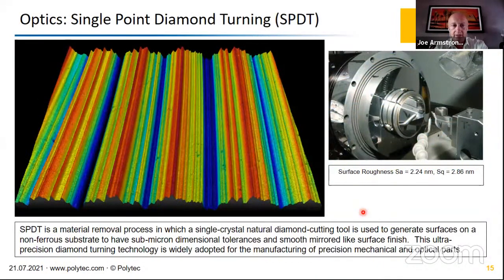That makes us particularly suitable for applications like single point diamond turning, where you take a diamond-like tooltip, which is in the order of 1 or 2 microns in radius. You can then precision turn, control the texture and the shape of these surfaces. Here you can easily get down to a couple of nanometers in terms of texture, but they're quite demanding in terms of the types of shapes that you might want to produce.